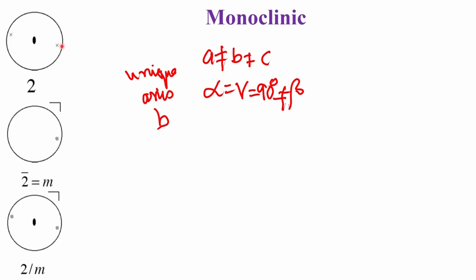The equivalent points are x, y, z, and I want you to figure out what the equivalent point is given the two-fold operation. Obviously, the two-fold operation will keep the identity of the object the same, that means there is no inversion here. So, the value of x will go to minus x, the value of z will go to minus z, because the B axis is unique, there is no change of the y value.